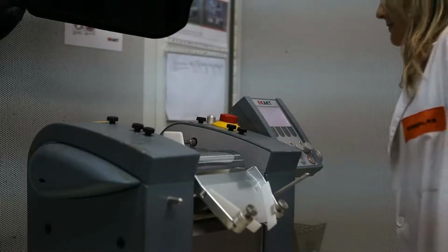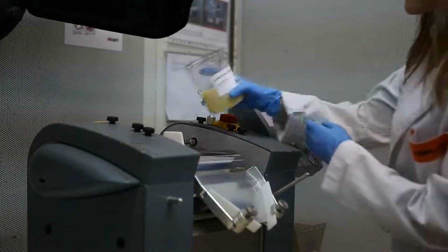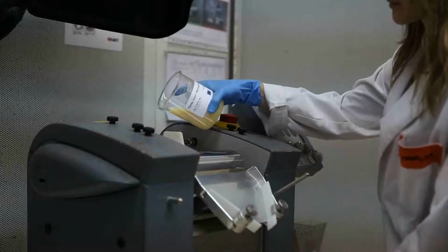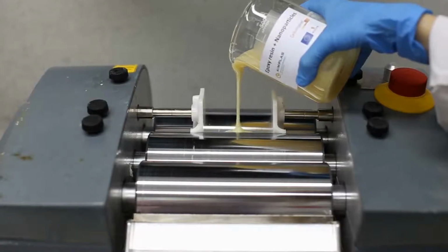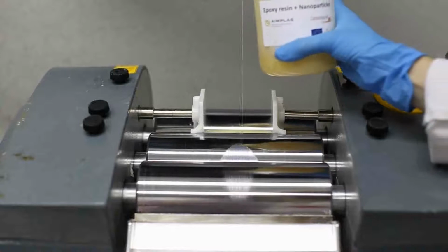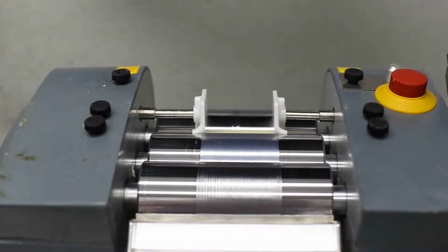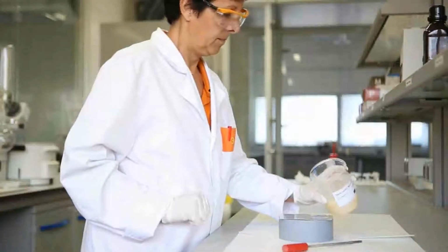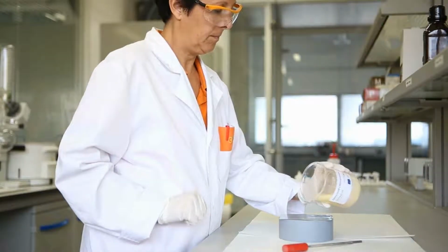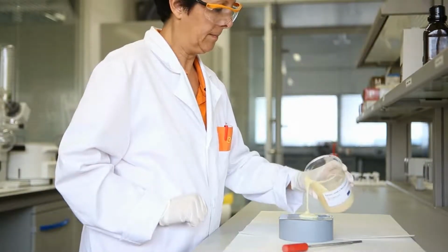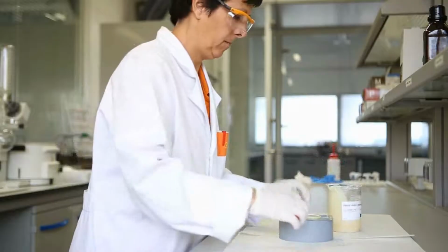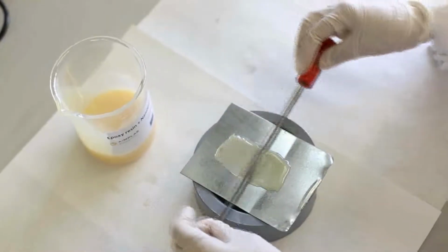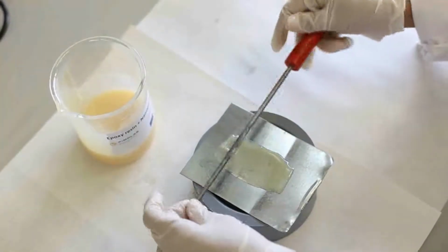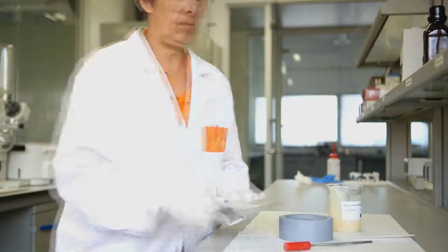The development begins with the selection of nanoparticles and their incorporation into resin using a 3-roll calender at low contents, being that an advantage compared with micrometric additives. After achieving a correct nanoparticle dispersion and distribution in the matrix, the coating is applied on the piece in an easy step. Afterwards, the coating is cured by thermal action, resulting in an optimal protection against external agents.